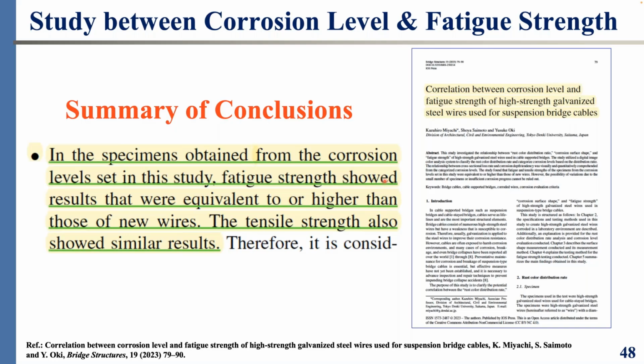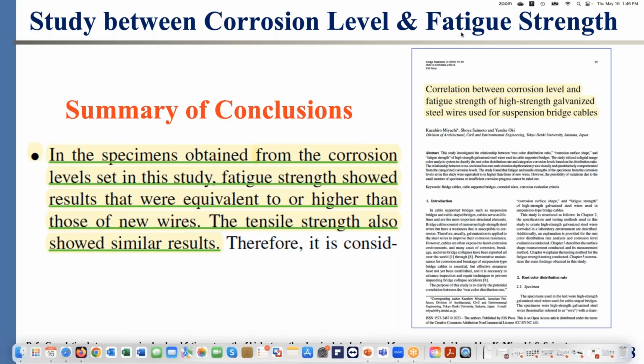Actually, I reference here a paper by a group of researchers from Tokyo Denki University in Japan, and they studied the correlation between corrosion and fatigue strength of high-strength galvanized steel wires used for suspension bridge cables. And here is a snippet of the summary of the conclusion. It says that in the specimens obtained from the corrosion levels set in this study, fatigue strength showed results that were equivalent to or higher than those of new wires. The tensile strength also showed similar results. So there you go. This is the kind of discrepancy that you would see with the visual corrosion.